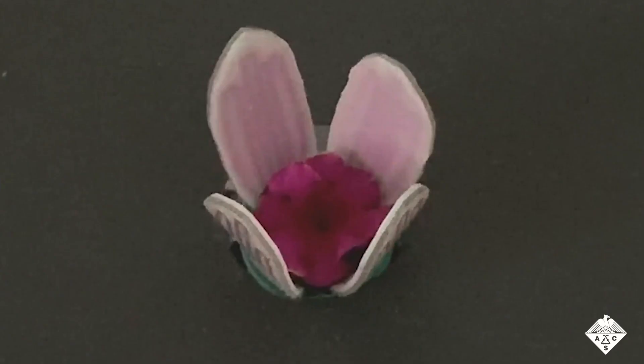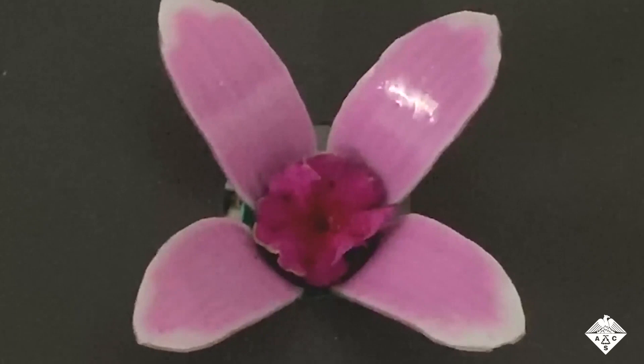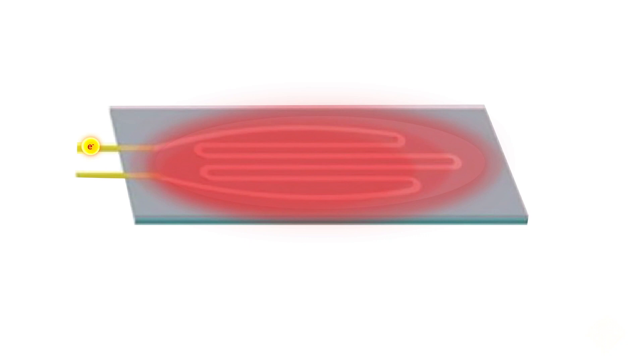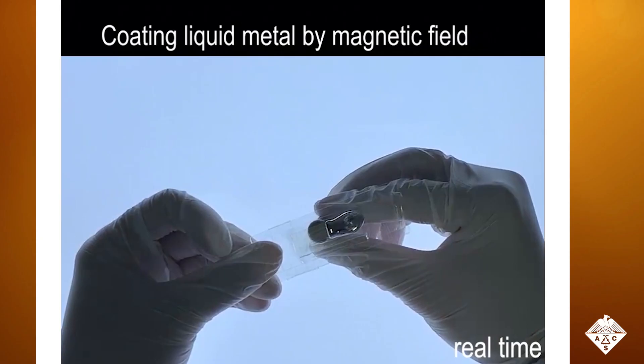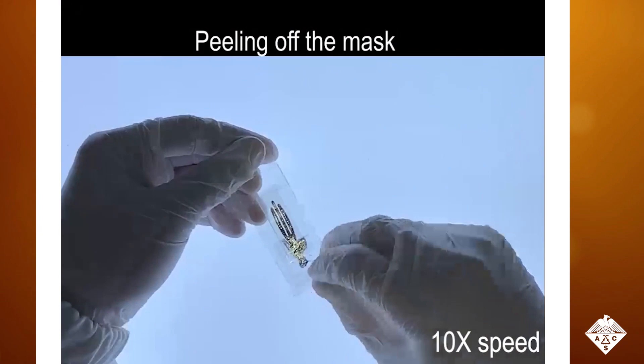To make a soft material capable of autonomous movement, Chao Zhao, Hong Liu, and colleagues printed liquid metal into circuits on polymers that undergo large changes to their shapes when heated or cooled. These scientists had previously explored using liquid metals to create thin, flexible circuits. These circuits quickly heat up when an electric current is generated, either from an electrical source or from pressure applied to the circuit. When the soft circuits are stretched, the current drops, cooling the material. The researchers applied a nickel-infused liquid metal onto a soft polymer film and magnetically moved the liquid into lines to form an uninterrupted circuit.